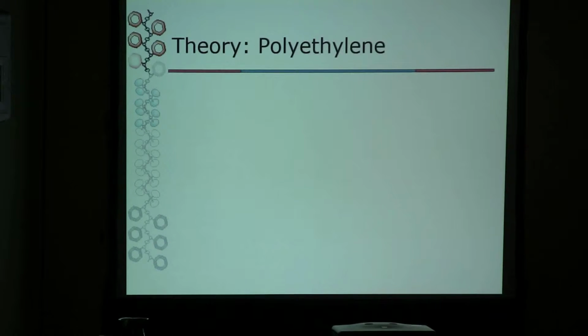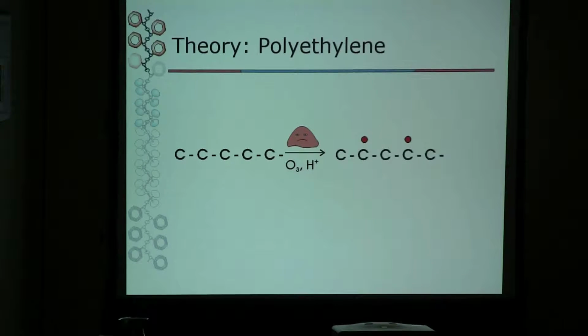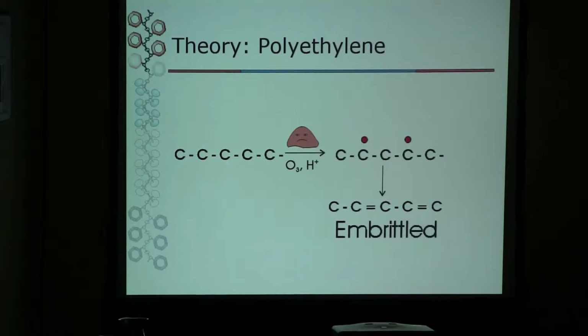So here's the theory, and it's very simple polymer chemistry. The simplest of the polymers is just thousands of carbon units in a row, and this is polyethylene. In the presence of macrophages that secrete their superoxide and bring the pH down to 1, you form free radicals on the backbone. And the free radicals begin to conjugate. And if you have a single bond, if you imagine 2 pieces of wood with a nail through it, you can rotate the pieces of wood. But if you put 2 nails through it, you can't rotate. And this is what happens in polymers. If you have double bonds, you can't rotate. And this manifests as embrittlement.